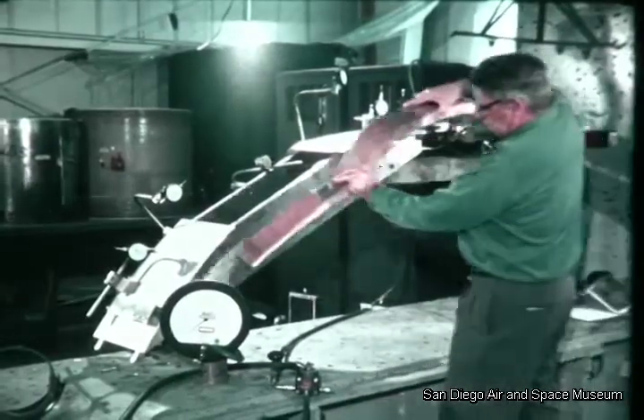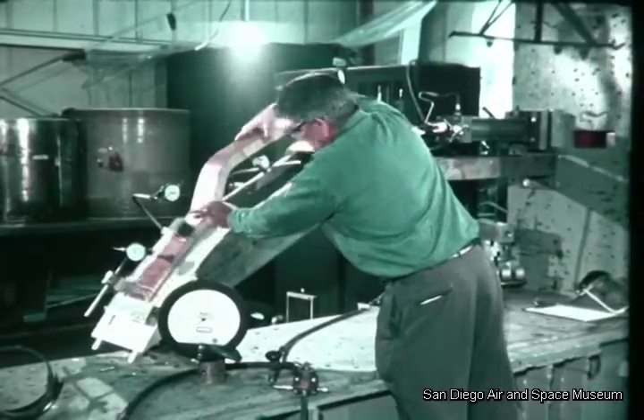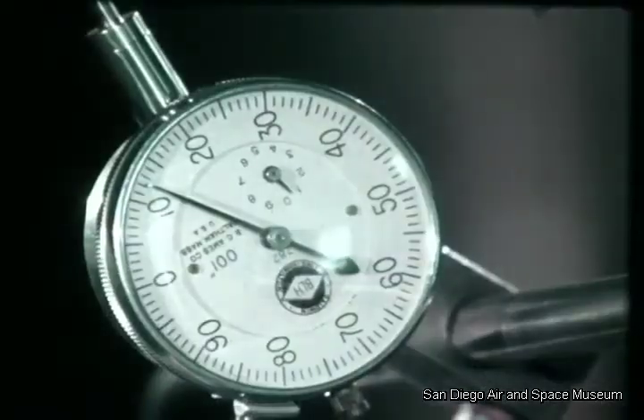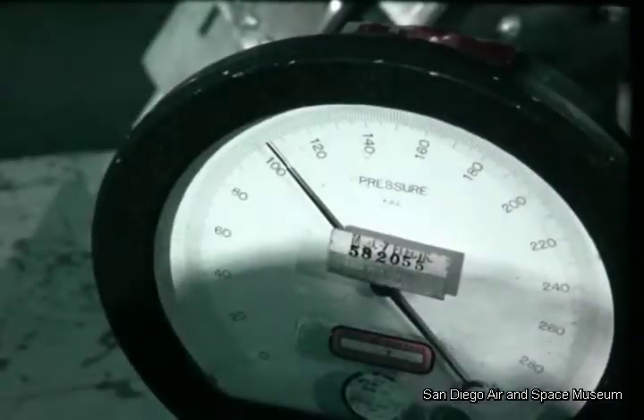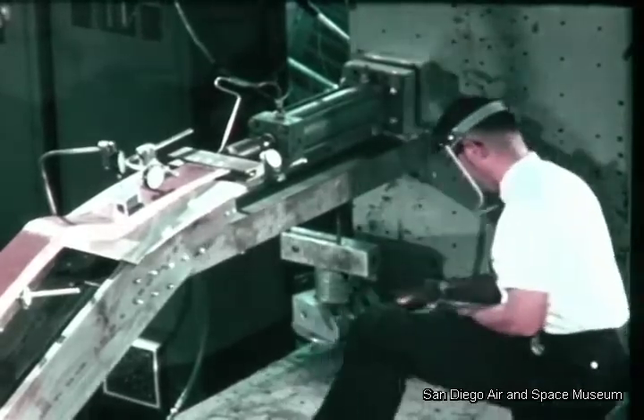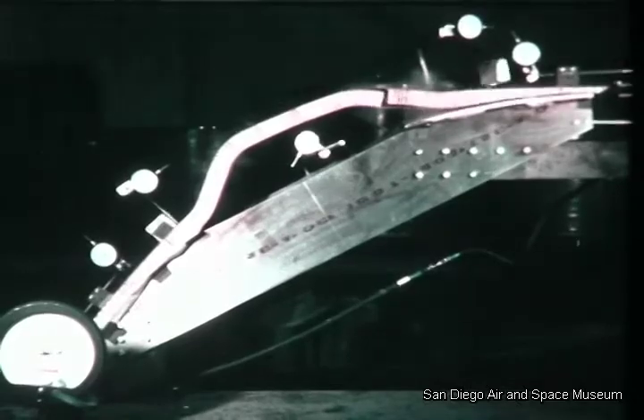Temperature of the Centaur tank and the hydraulic ram applies control hoop tension loads. Deflection gauges measure radial and circumferential displacement at design limit and ultimate loads. Data from the 12 specimens tested to destruction indicated a need for an increase in honeycomb core and skin thickness.